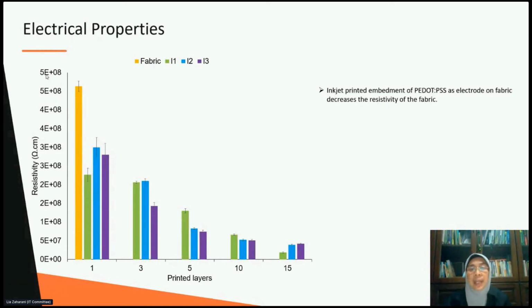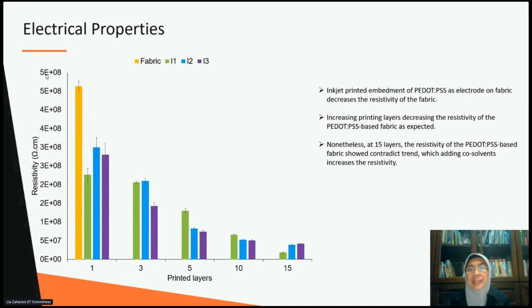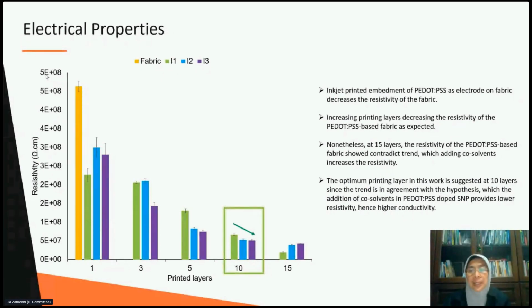Ink 3, on the other hand, reduces resistivity when printing up to 10 layers due to the phase separation between PEDOT and PSS, caused by the reduction of Coulombic interactions between them, since a screening effect between the positively charged PEDOT chain and the negatively charged PSS chain occurs when adding ethanol and EG into the formulation. All right, so the optimal printing layer in this work is suggested at 10 layers, since the trend is in agreement with the hypothesis that the addition of co-solvent in PEDOT:PSS provides lower resistivity, hence making the conductivity higher.